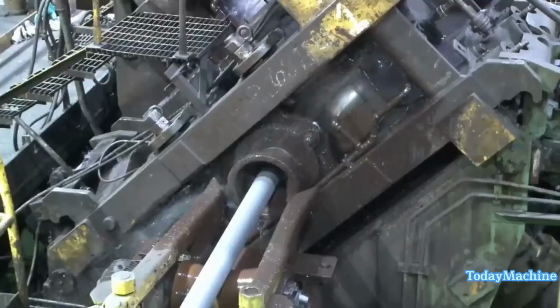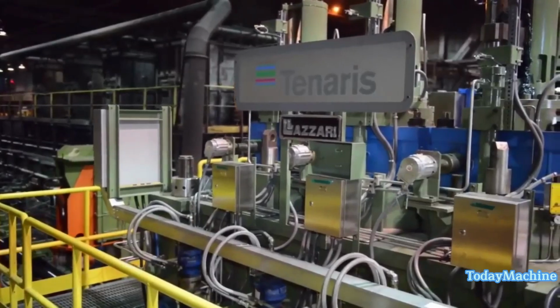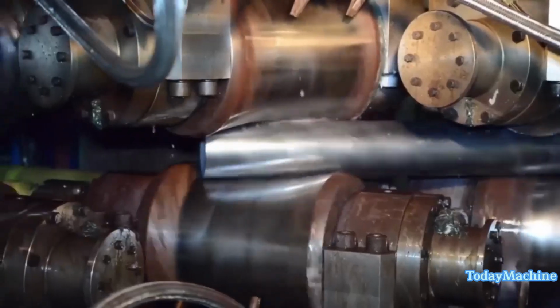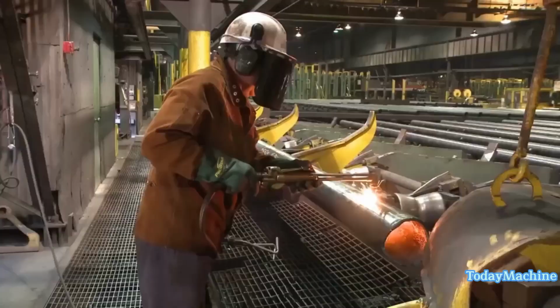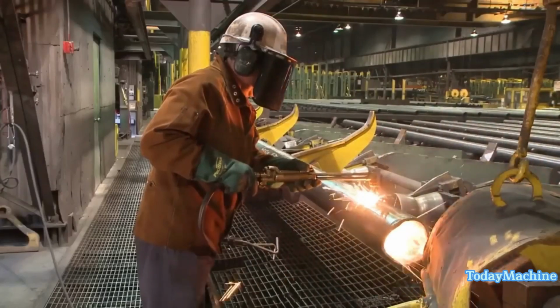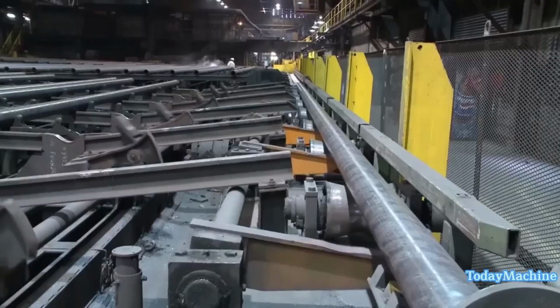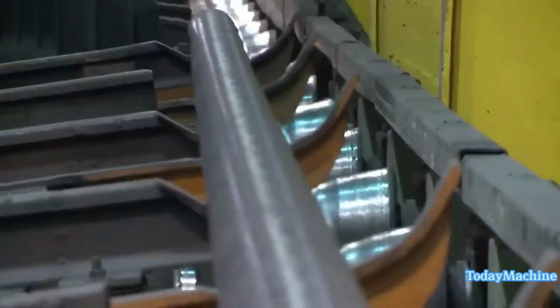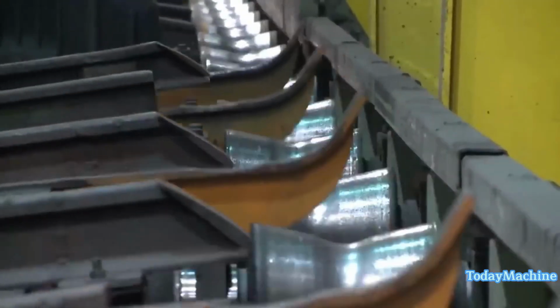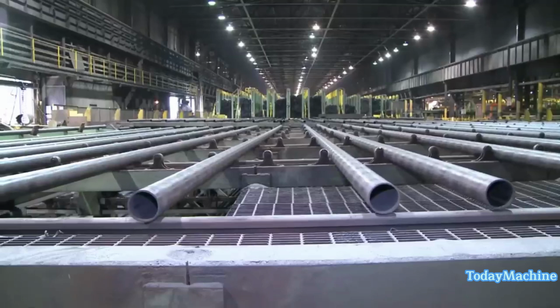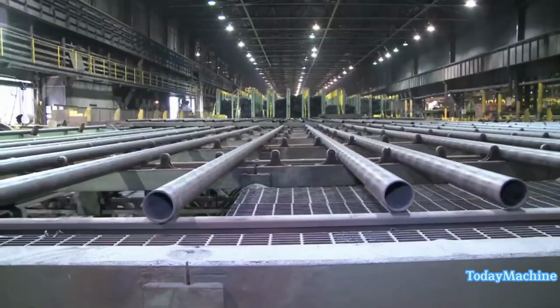After quenching and tempering, the pipe passes through a 3-stand resizing mill that calibrates the outside diameter to final tolerances. The pipe is then straightened on a rotary straightener while still hot. Samples are taken for testing of physical properties before the heat-treated and tempered pipe is transferred to a cooling bed and cooled to ambient temperature.